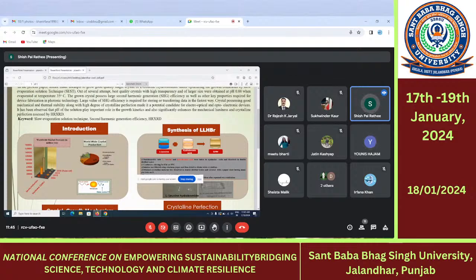First, we synthesize the L-leucine hydrobromide single crystal. We take L-leucine in a beaker, dissolve it in distilled water, and then add the aqueous solution of hydrobromic acid. After that we use the slow evaporation solution technique to get the salt synthesized. The synthesized salt is dissolved according to the solubility of L-leucine hydrobromide and kept for constant evaporation. In the first attempt, we tried to grow the crystal at ordinary condition, but later we tried to grow the crystal at different values of pH, because the quality of the crystal grown at ordinary condition is not good, as shown in this figure.